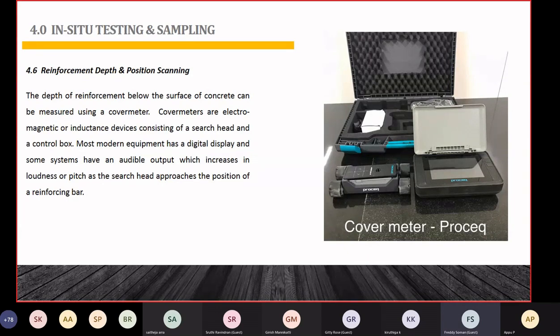In cases when we lack structural drawings and as-built drawings, it is applicable to find out the reinforcement position, orientation, and even the diameter of the rebars. We can find out the diameter of the rebars using this equipment, and also bar position, and at what depth it is embedded, that is cover, and the orientation, using this rebar scanner.